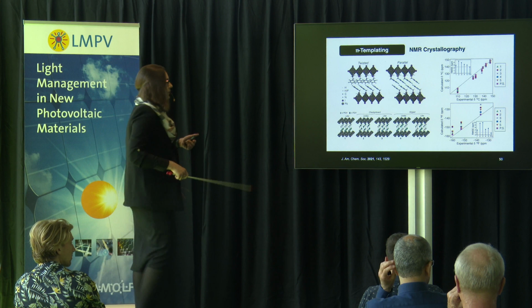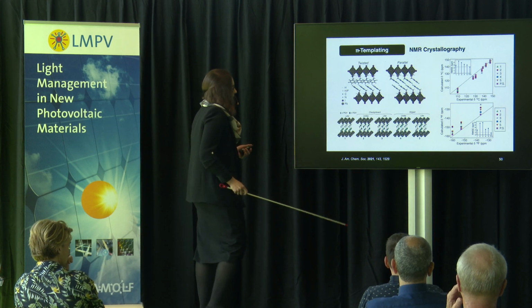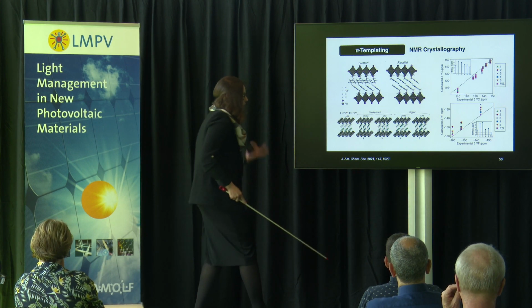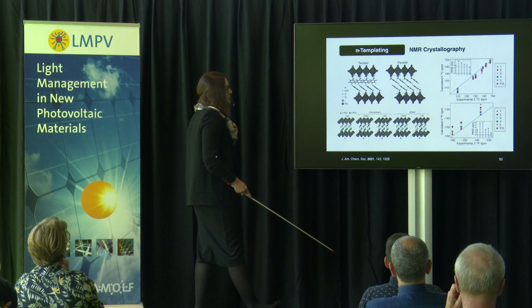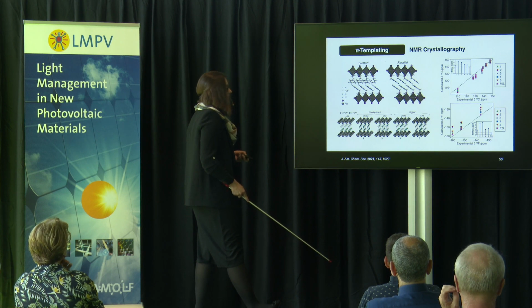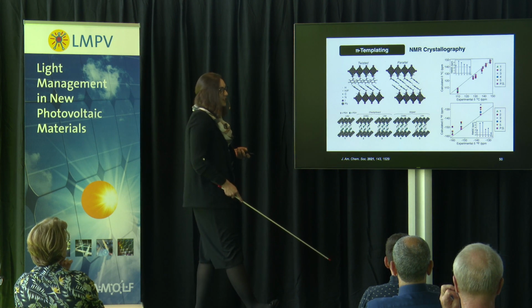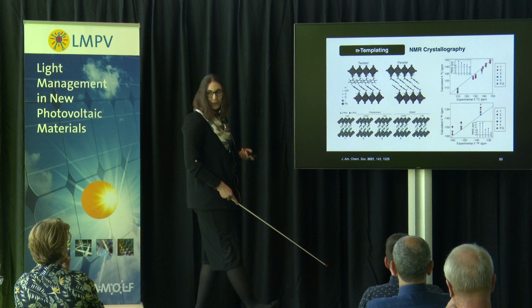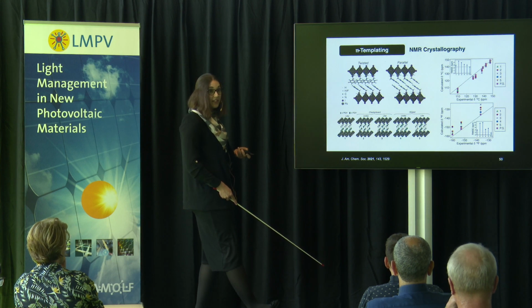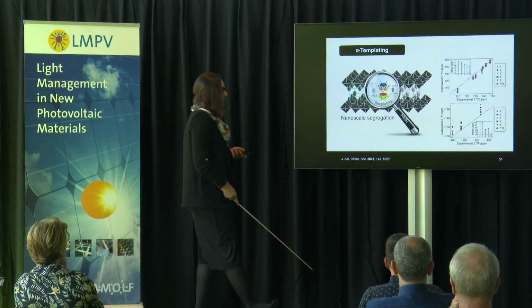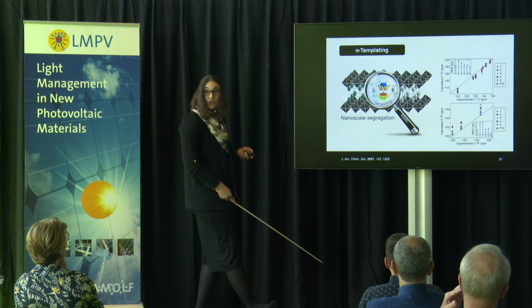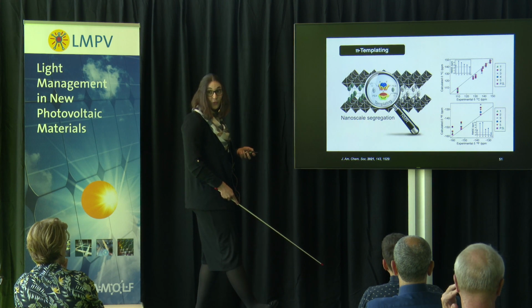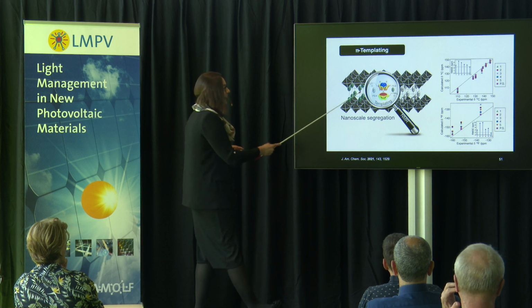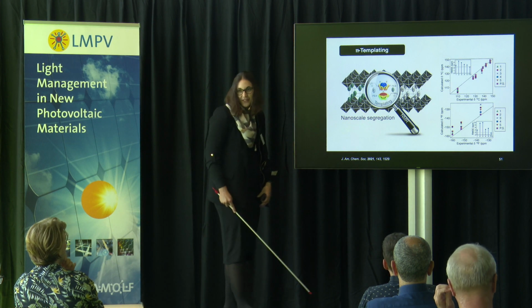But when we look carefully into what NMR crystallography offers us, we see that the best match in this case, in fact, comes from the mixtures of neat arene and perfluoroarene moieties, suggesting that these systems are in fact nanosegregated. They feature narcissistic self-sorting that favors alike systems inside the solid state.